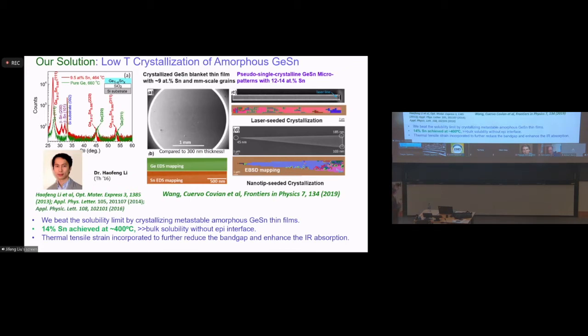And then we anneal it, which drives this to the solid state, instead of going from liquid through a solidification process. We found that you can crystallize the material very well. The figure here is not very clear, but can you see the green boundaries in the SEM? Scale bar is 1 millimeter. What's interesting is that the thickness is only 300 nanometers. Usually when crystallizing semiconductor thin films, the rule of thumb is that the thickness is comparable to the grain size. Here you get a grain size much, much greater than the thickness.